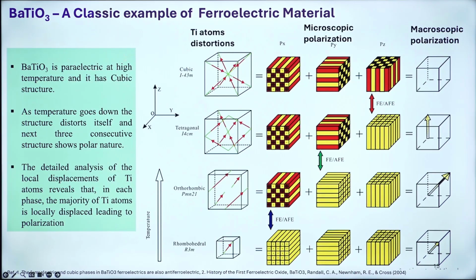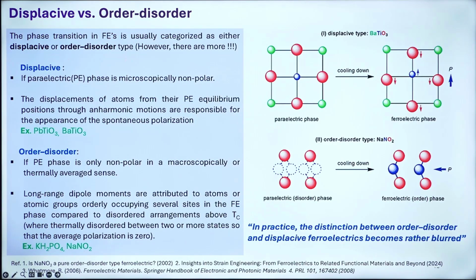Okay, so from tetragonal onwards we start getting signals of polarization in a bulk, and orthorhombic is much more, and when it comes to the low temperature phase, it is very ordered, and we do see all the dipoles aligned in a particular direction. Yeah, so now the interesting point here is displacive versus order-disorder. These are the two key players to understand the mechanism of ferroelectricity.